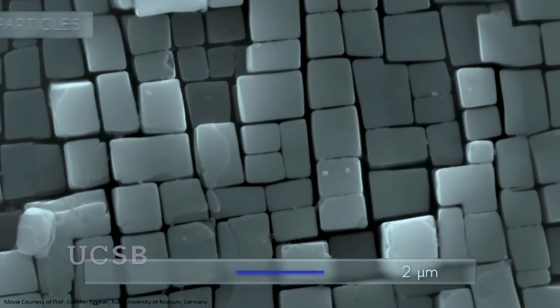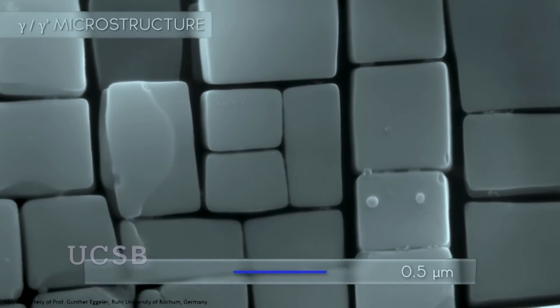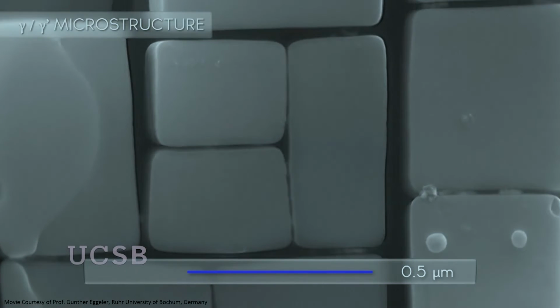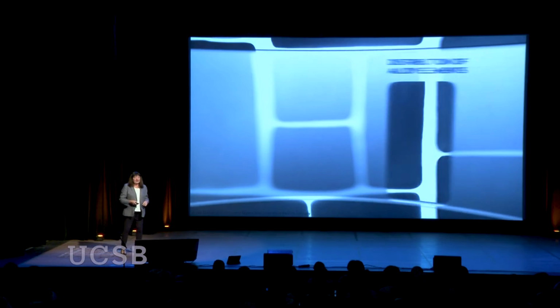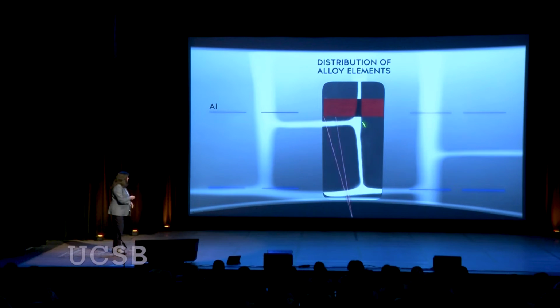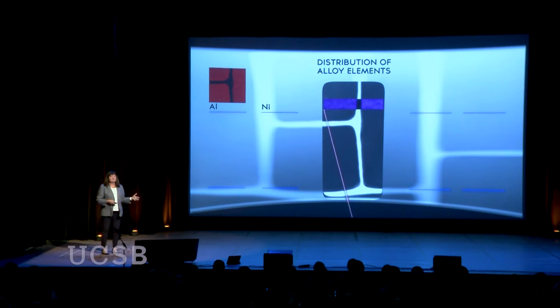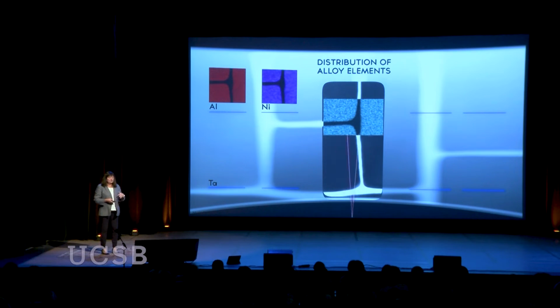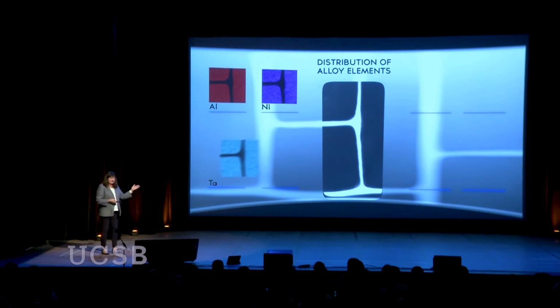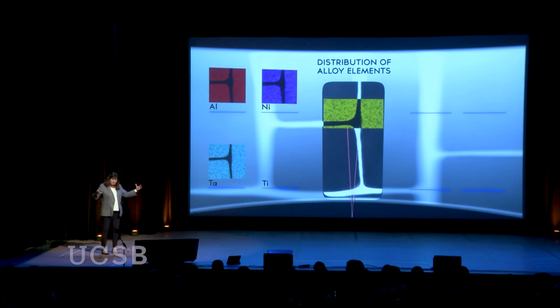microscopes. And so here we're down to the 2-micron scale, and you can see all these blocks. And these are actually a different crystal structure than the material around them. This is what we'd refer to as a 2-phase material. And these blocks of material are what allow the nickel alloys to be so strong and operate up to 85% of their melting temperature.